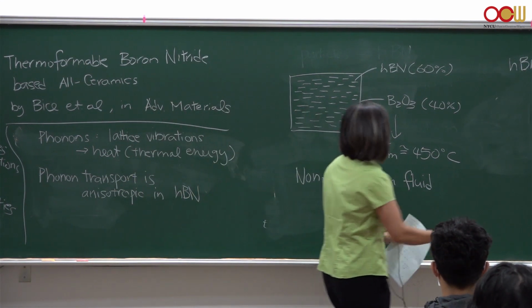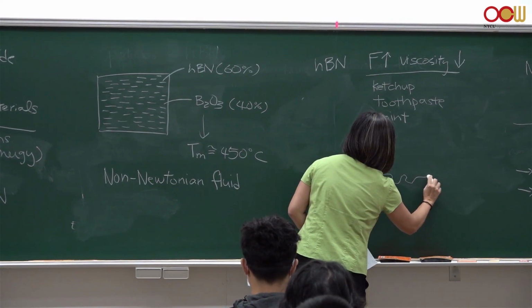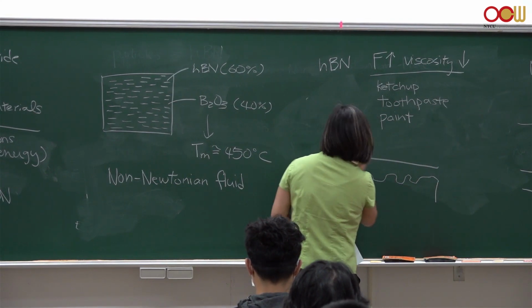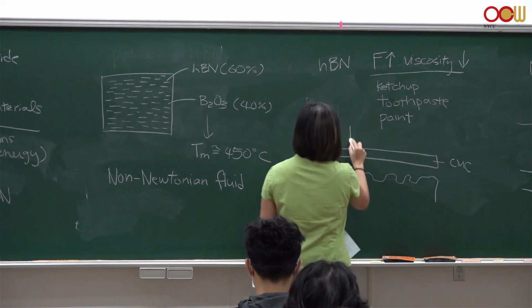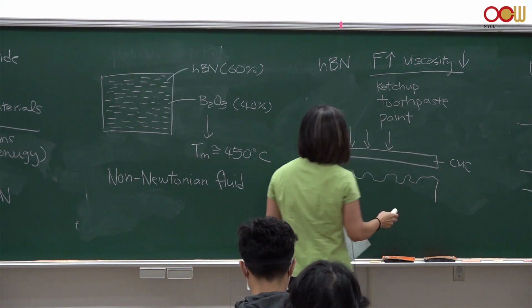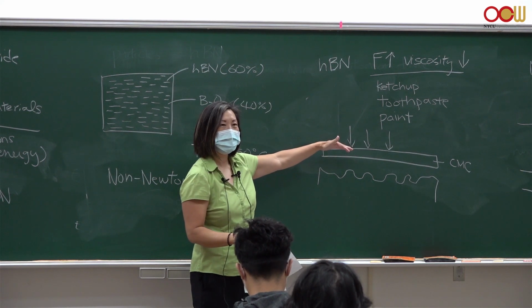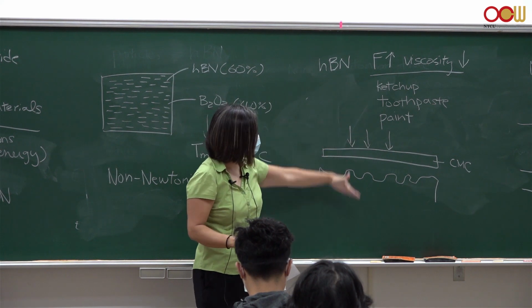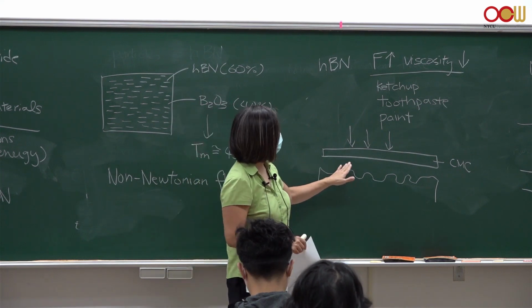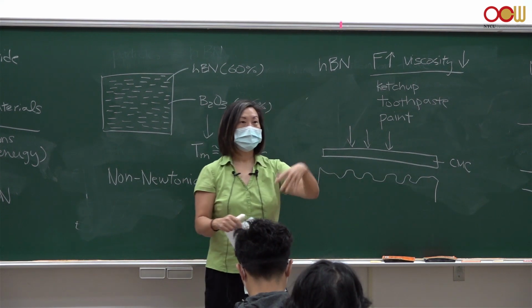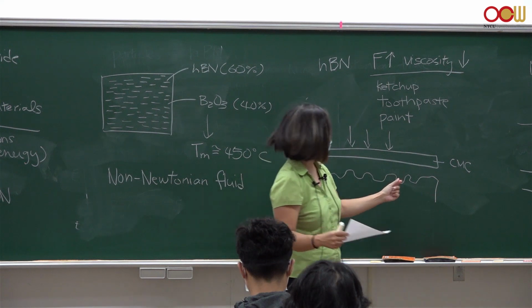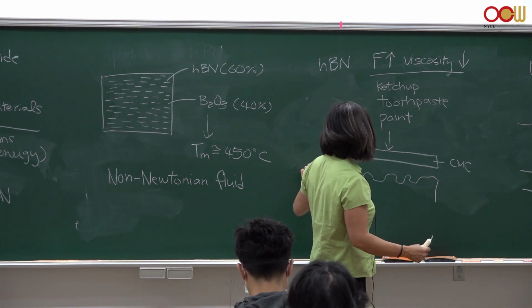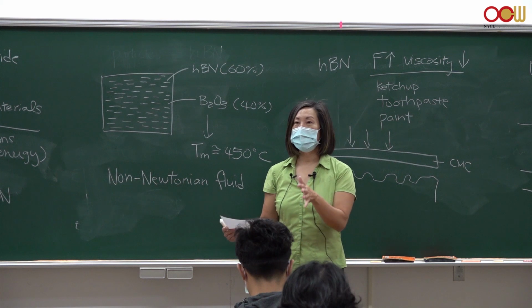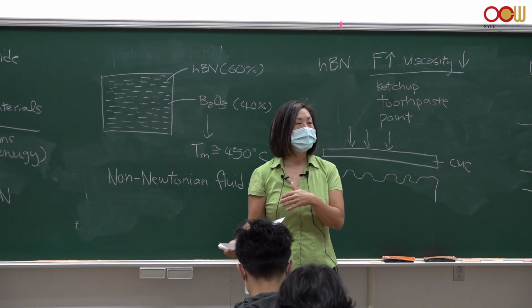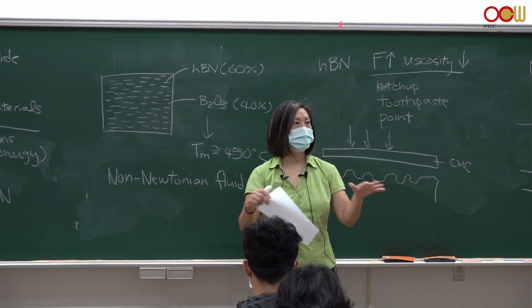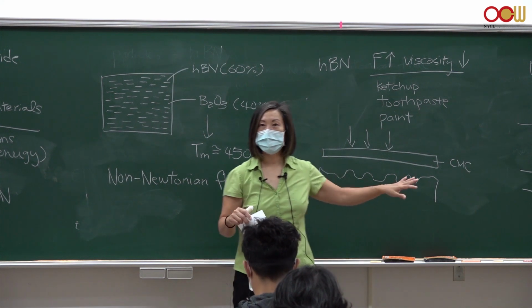And so they're able to take a mold of some complex shape, take the boron nitride CMC, heat it, of course, to above 450 degrees C, apply pressure, and cause it to flow over the mold, release the pressure, and now you have a ceramic material that's in this new shape. And in the paper that I shared with you on E3, they show pictures of what they're able to make with this kind of process.